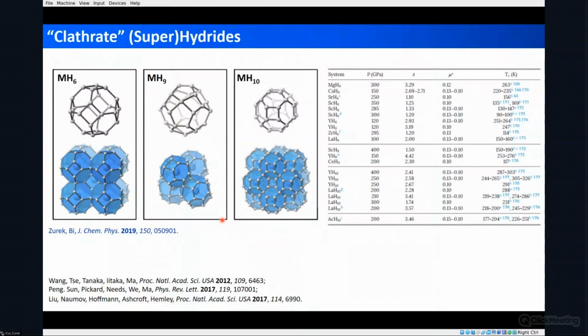And then finally on to these clathrate superhydrides, as they are called. They have these types of three-dimensional lattices where you have really weak hydrogen bonds forming in the lattice, and then the metal atoms stuck in the center and clathrated within these cages. And they are predicted to have the highest TCs, of course, only at very high pressures, but some TCs actually reaching that of room temperature.